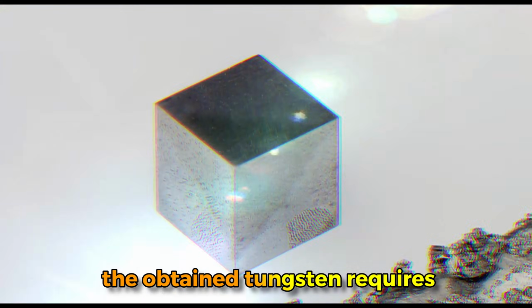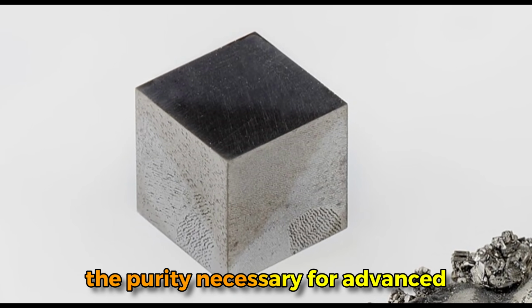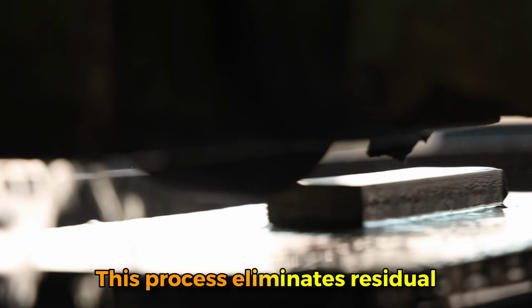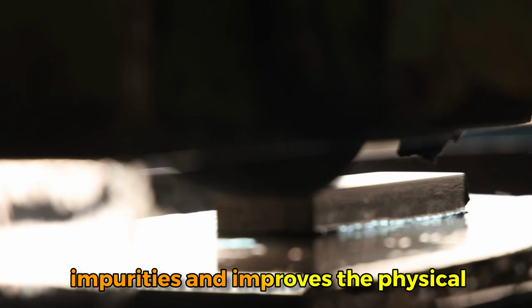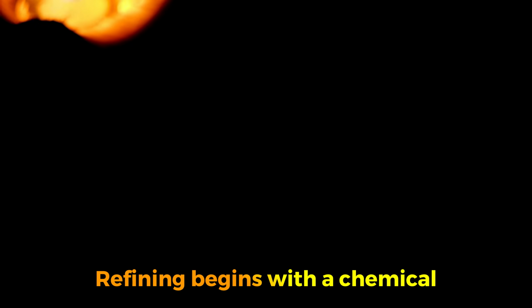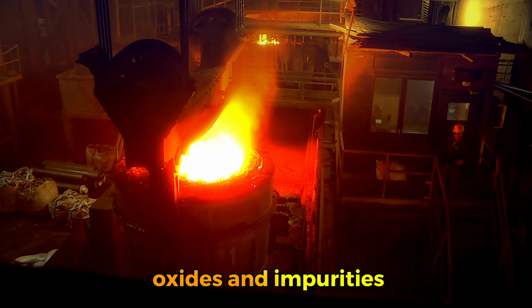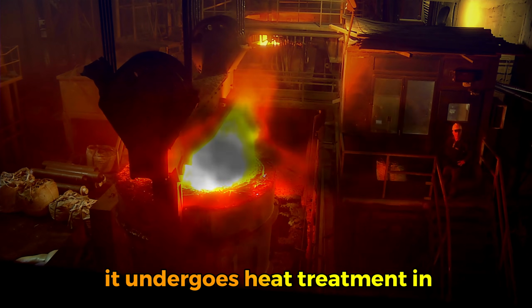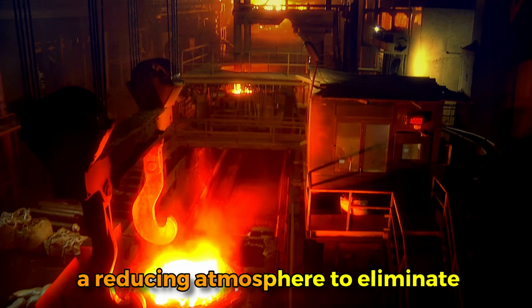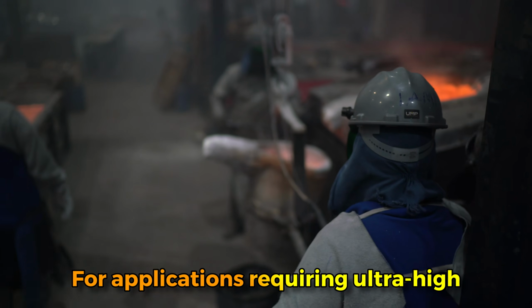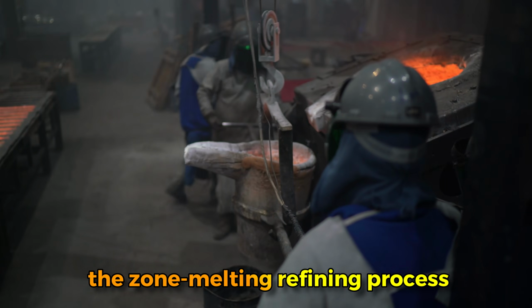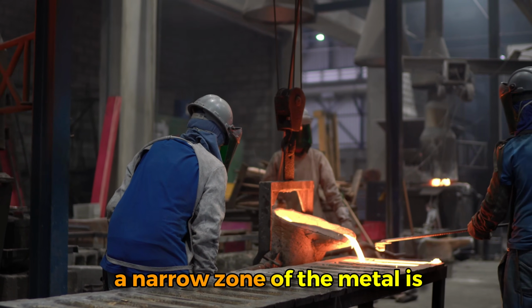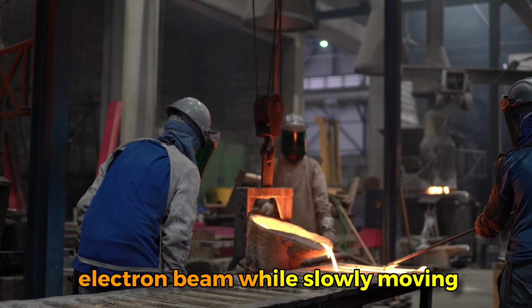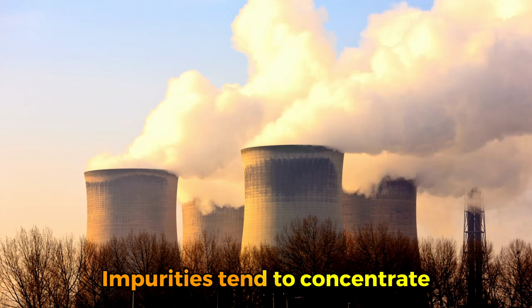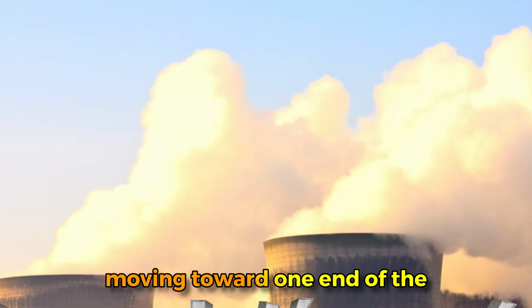After reduction, the obtained tungsten requires additional refining to reach the purity necessary for advanced industrial applications. This process eliminates residual impurities and improves the physical and mechanical properties of the metal. Refining begins with a chemical washing of the metallic powder using diluted acidic solutions that eliminate traces of surface oxides and impurities. Subsequently, it undergoes heat treatment in a reducing atmosphere to eliminate volatile impurities. For applications requiring ultra-high purity, the zone melting refining process is employed. In this method, a narrow zone of the metal is melted by induction heating or electron beam while slowly moving along a tungsten bar. Impurities tend to concentrate in the molten zone, moving toward one end of the bar.